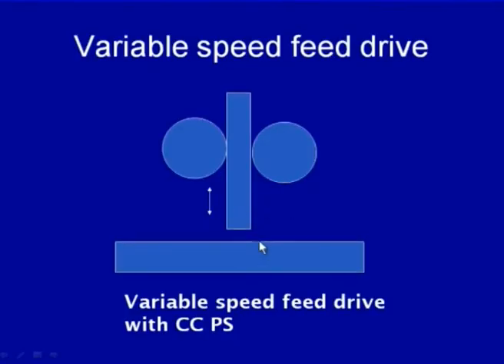So, if the arc gap is increased, this increase in arc gap will increase the arc voltage, and this increase in arc voltage is used as input to reduce the current being fed in the motor drive system to drive these rollers, so that the speed of these rollers can be reduced, because the speed of these rollers decides the speed at which the electrode is being fed during arc welding. So, reduction in the speed of these rollers will reduce the rate at which the electrode is being fed.